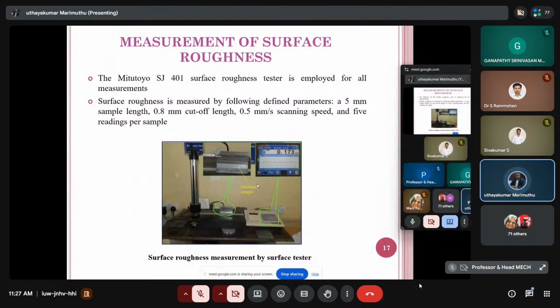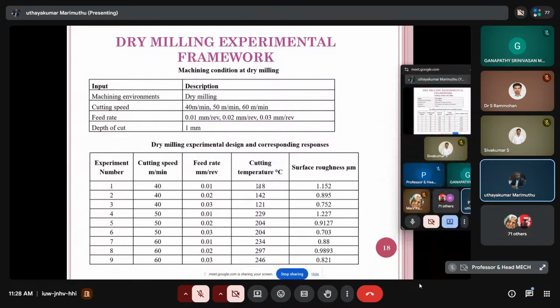Next one is the surface roughness measurement. A Mitutoyo SJ-401 surface roughness tester is employed to measure the surface roughness. We are reporting the arithmetic average, the Ra value, and the specification is reported here: 5 mm sample length and 0.8 mm cutoff length. We did this for every machined surface, and the roughness value is reported.